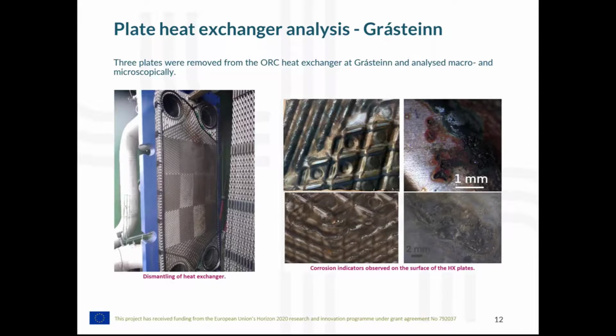So for Grásteinn, after an ORC demonstration, we opened up the heat exchanger, dismantled it, and took 3 plates from different locations within the heat exchanger, and we focused on the most affected sites. So first we analyzed it macroscopically, looking at the plates itself. Then we cut out smaller samples to analyze in optical microscopy and scanning electron microscopy. And on the right there, you can see 4 pictures from an optical microscope with some corrosion indicators on the surface of the plates, and especially the one on the top right shows some pitting occurring in the material.